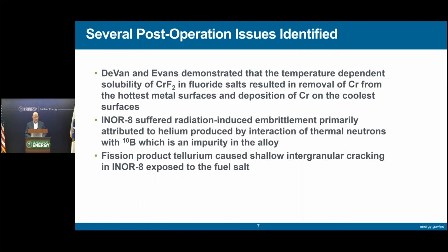There are several post-operation issues identified on this slide. DeVan and Evans demonstrated the temperature-dependent solubility of chromium fluoride in fluoride salts resulted in removal of chromium from the hottest metal surfaces and deposition of chromium on the coolest surfaces.